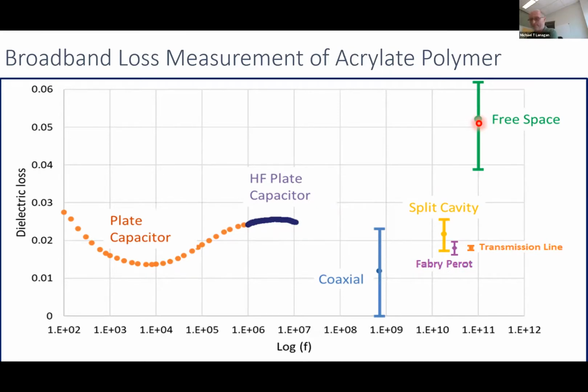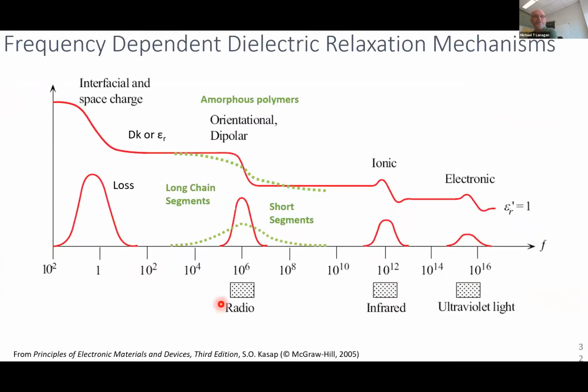One thing we've learned from these types of measurements is that these neat little interpretations of a dipolar response aren't so trivial. Because of the complex nature of these polymers, we really have to think about the long chains and short segments and how they smear out this response. And these tails really start pushing up into the 5G range. So as we explore polymers, it's going to be really important to understand the structure of those polymers and how some of these orientation or dipolar responses push loss up in this frequency range of interest. And so, there are specific materials that we're looking at for 5G applications.